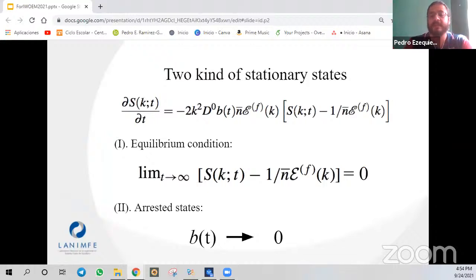The most important characteristic of the NE-SCGLE theory is that it is able to predict two kinds of stationary states as a result of a relaxation process. Consider the main equation of the time-dependent structure factor at the top of the screen. If we ask for the stationary solutions, two possibilities arise. If the bracket becomes 0, then we are at equilibrium. In contrast, if the time-dependent mobility goes to 0, then we obtain a non-equilibrated, arrested stationary state, which can be identified with glassy states.